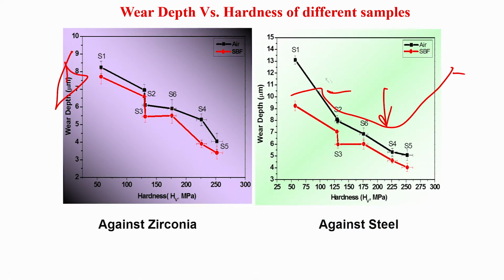In case of steel, again what we have noticed is that if you increase the hardness of the material, typically wear depth decreases. But what is interesting here is that wear is still typically more in case of pure HDPE, but when it goes to S2 to S5, the wear rate is 5 micron or below.